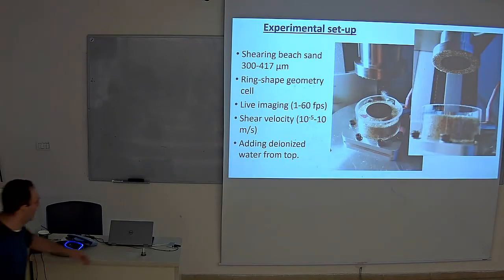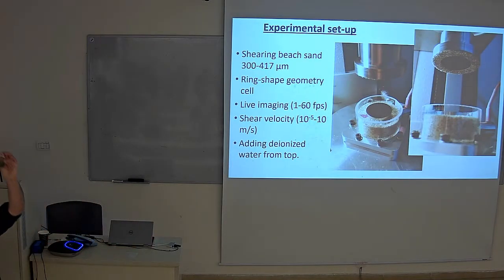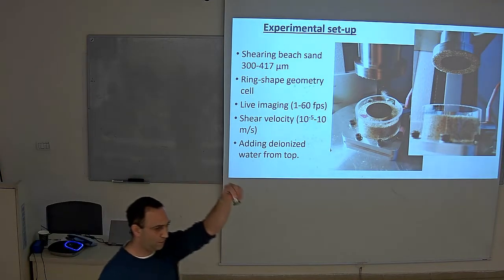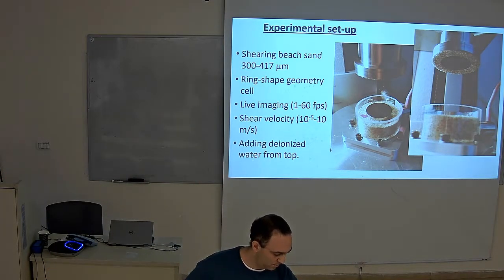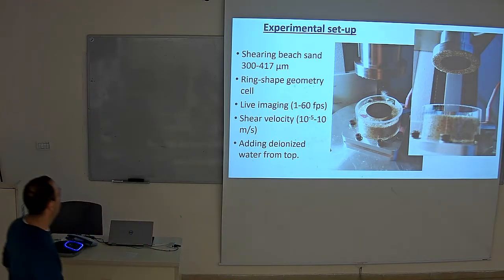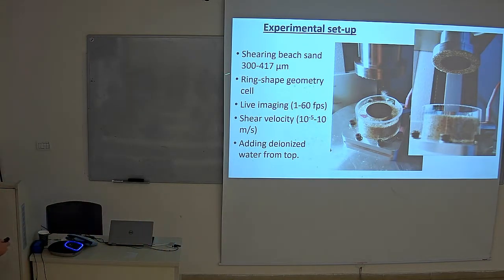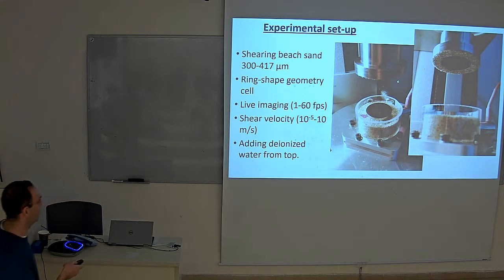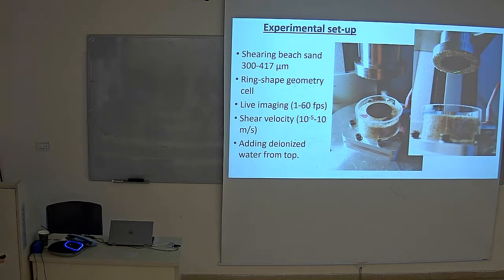So the system looks like this, and I will pass around an example of the rotor we are using. This is the moving rotor on top. We are shearing beach sand in the size of 300 to 417 microns. It's beach sand from Santa Cruz. We just collected it there. We are gluing the beach sand to the rotor, as you will see in the sample that I'm passing here, in order to move the deformation into the grains, and not just on the boundary between the steel rotor and the grains.